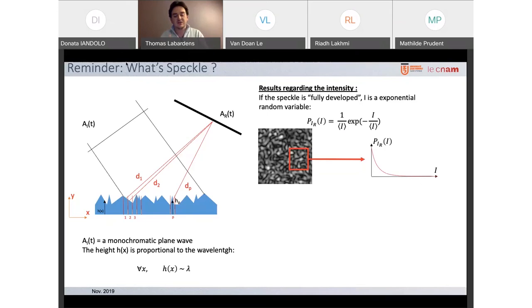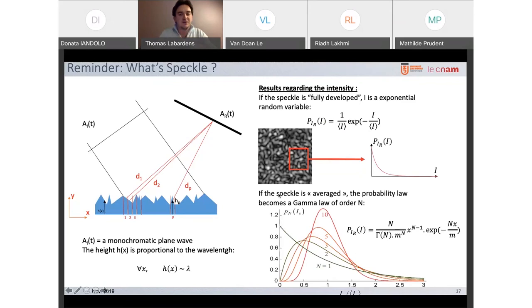But when you degrade the signal, for example, if the wave plane isn't that plane, or if you have some characteristic of the surface, or maybe the optics aren't perfect, then you get a speckle that is a bit averaged, and the probability law becomes a gamma law. Of course the ideal one is still an exponential random variable, but if you degrade the speckle, then you get this law. So why am I talking about it? It's because the gamma law is actually a tool that we can use to evaluate whether we have speckle or not.